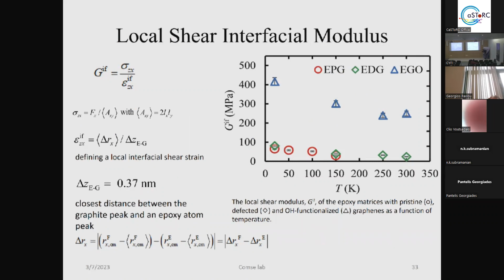the functionalization of the interfaces. They're working like mechanical blocking. They're working like brushes that block with the polar groups of the epoxy. And as we try to pull it out, this is stacking and it has better adhesiveness. And that's why we can see bigger values for the blue triangles for the EGO. On the other hand, we can see that the pristine graphene at room temperature disappears. We saw that, because of the totally clean surface, it has 0 adhesiveness, as you can see, and barely the EDG survives.